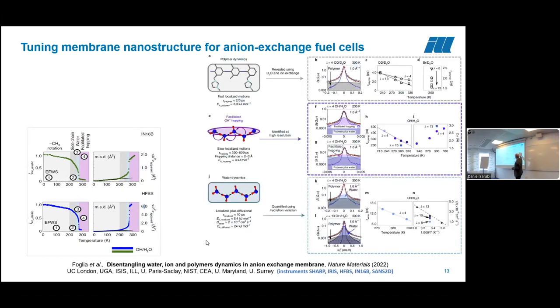I'm not going to go through this, but I want to point out that it was a neat experiment because they were able to focus in on the polymer dynamics by replacing water and hydroxyl ions by their deuterium counterparts. And you saw the dynamics here. They were able to use a very high resolution instrument at the ILL called IN16B in order to confirm the presence of hydroxyl ion popping or proton movement. And then they changed the water content of their cell during the experiment to get the water dynamics of the bulk water.